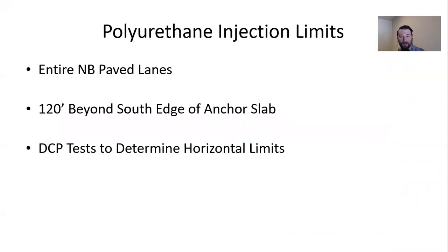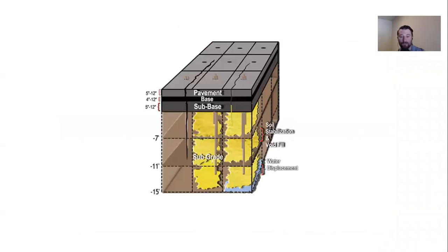I'm going to go back here just a second to go into a little bit more detail on this process. I've described the material that's used, but in order to uniformly densify the soils, what we have to do is inject at multiple depths. Unlike what's more common with other forms of compaction grouting, displacement grouting, jet grouting, instead of drilling to the full depth of the issue and pulling our pipes out as we inject, we place multiple pipes at varying depth intervals, because from the tip of our injection pipe, we only expect to influence soil within the first 3 feet.